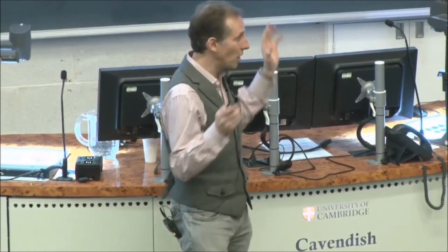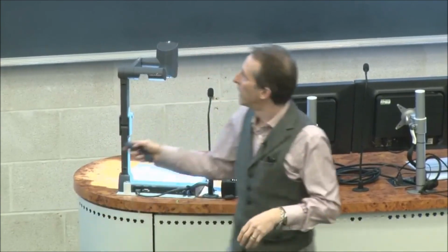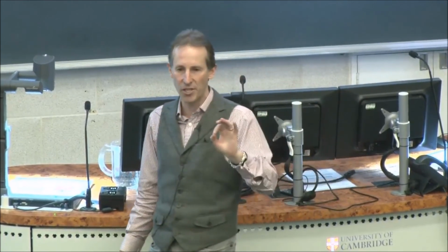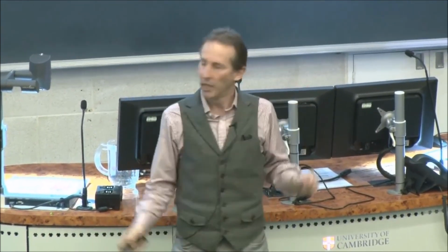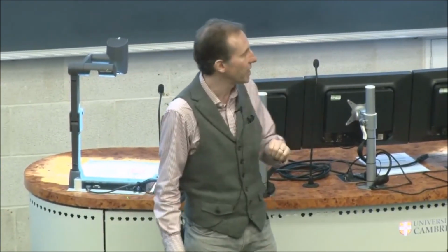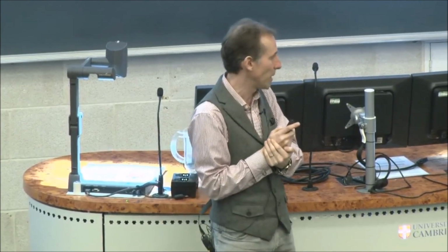No, I mean, you can actually do a lot of this. We have a model here which looks exactly like circuit theory, right? So essentially, you can think of the nanoparticle as an inductance and a capacitance, which gives you a resonant frequency. And you can couple it to another one through this capacitive coupling there, and you can use that model to basically predict where the light is. It's not obvious you could use these lumped elements, because at these size scales they're much smaller than the wavelength of light, but it's a reasonable approximation. Okay.